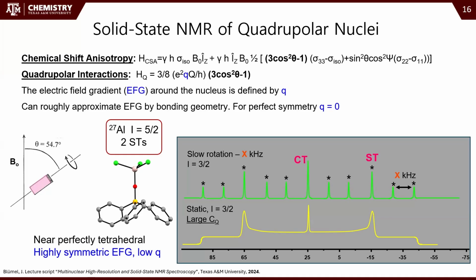Quadrupolar interactions are also susceptible to magic angle spinning, so we also get discrete rotational sidebands. So we get improved resolution and shorter measurement times with those. And the strength of the quadrupolar interaction, if you're looking at the same nucleus, is going to be depending on the electric field gradient around the nucleus. So as we change to different phosphine oxides, you'll see that the size of the quadrupolar interactions will change. And that's just because of how symmetric the electronic environment around the aluminum is.